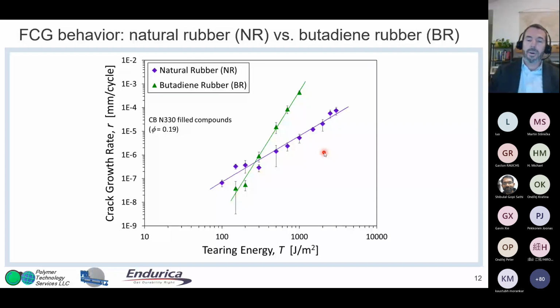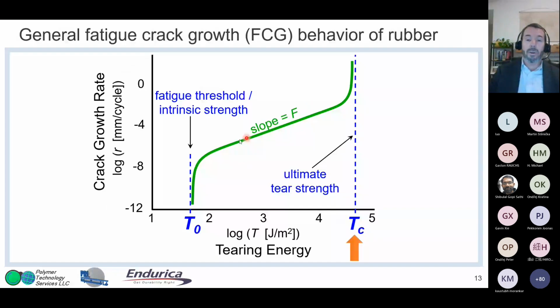So, and we'll return to this later, and maybe this can help us understand why sometimes natural rubber is better than butadiene rubber for certain type of durability applications, and then sometimes butadiene rubber is better than natural rubber. In particular, butadiene rubber is better than natural rubber for small scale abrasion, wear resistance of tires. And natural rubber, on the other hand, is much better for very high severity cut and chip type damage of rubbers. But again, characterizing the crack growth curve allows us to do such a comparison of materials. So what I just talked about is this middle part of the crack growth curve here.